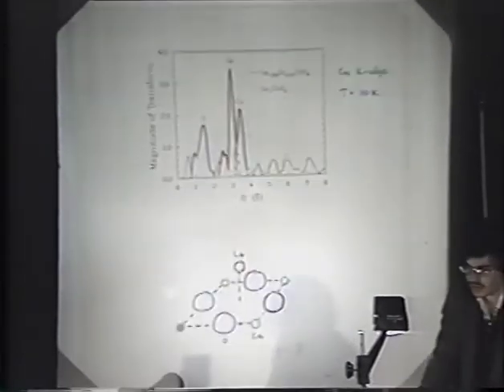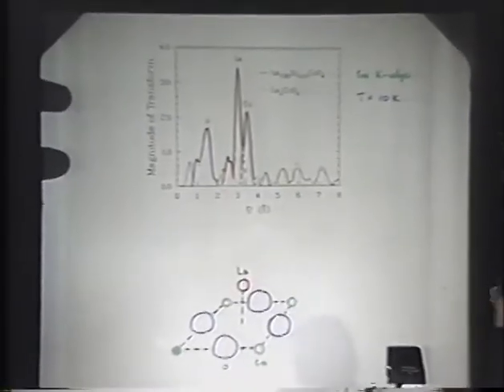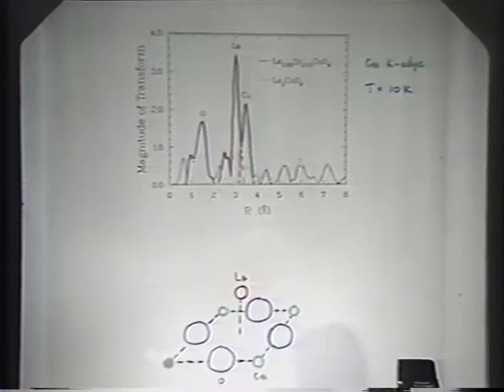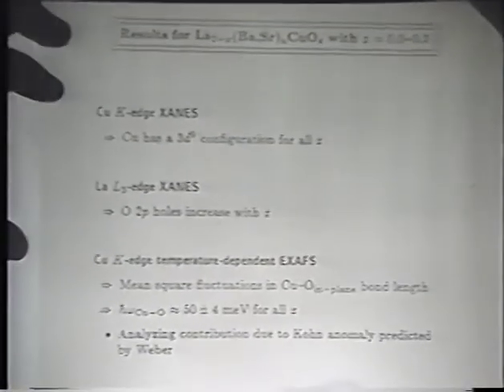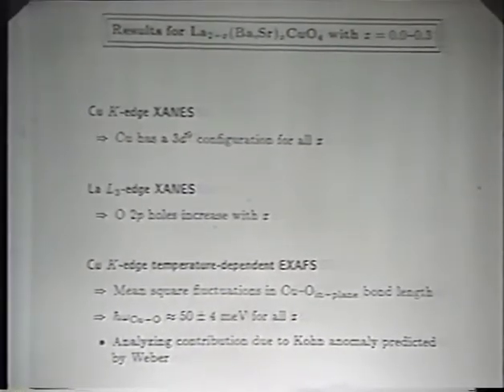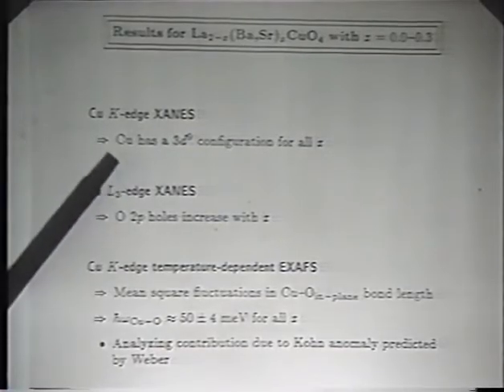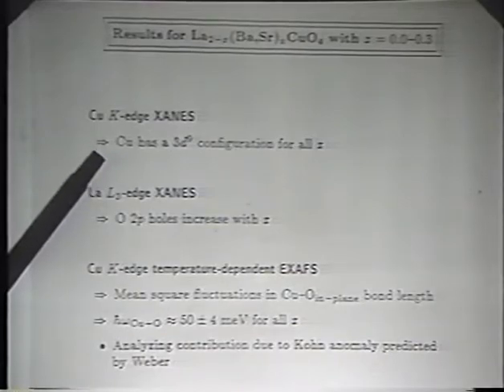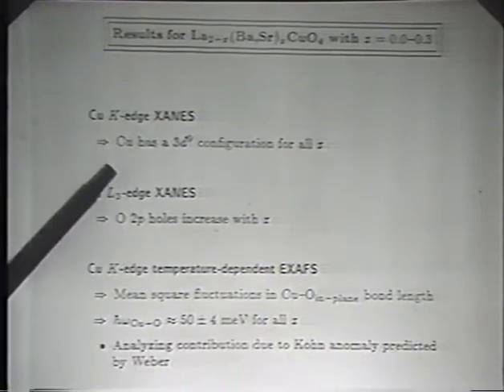It's just to show you we've measured the EXAFS in these materials at the copper K-edge from 10 degrees to 300 degrees. So then I'll just concentrate on the conclusions we've come to from our measurements. From the copper K edge, we find that there's no shift in the edge, and it lines up with a number of other nominally copper 2+ edges. And we conclude that the copper has a 3d9 configuration for all x.